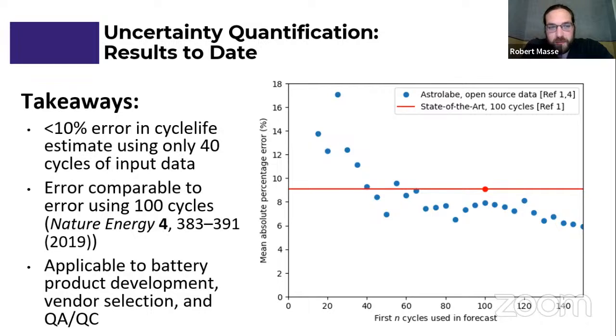So this model we've been able to extend to these different use cases and conditions, and we're able to get within 10% error using only 40 cycles worth of data. That improved upon the previous result, they're looking at 100 cycles as their state-of-the-art result from that particular Nature paper they reference. We've been able to get that down to about 6% error after n number of cycles. But yeah, basically we're looking at a 50 to 60% reduction in testing time if you want to go from 100 down to 40 or 50, or even much more than that if you implement this during vendor selection or product development, QA, QC, those types of applications.